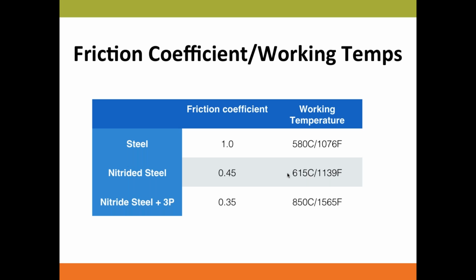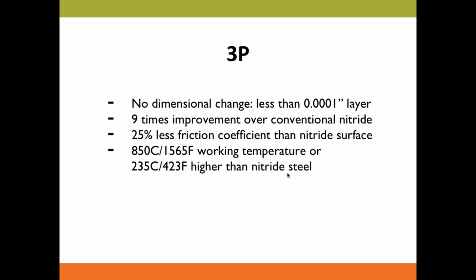Also, this one shows a little bit about the friction coefficient comparison between steels, nitride steels, and nitride steel plus 3P on top. You can see the friction coefficient is going to reduce further from nitride steels. And the working temperature, that means at what temperature the added 3P layer is going to decompose, is 850 degrees Celsius, which is higher than most die-casters would ever dream of on their pour temp.